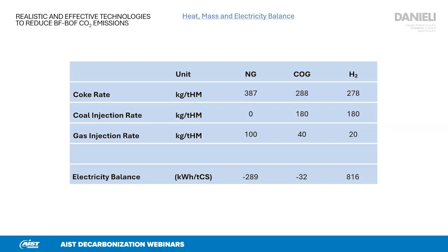More interestingly, let's look into the impact to the electricity balance. The potential export of electricity will double when injecting natural gas because more blast furnace gas at a higher calorific value will be produced. The export of electricity will be reduced to only 32 kilowatt hours when injecting coke oven gas because there would be no more coke oven gas for combustion in power plant to produce electricity. And far worse is actually the electricity balance when injecting hydrogen. Then we would need to factor in the usage of more than 800 kilowatt hours to produce 1 ton of crude steel by means of injecting of 20 kilos of hydrogen.